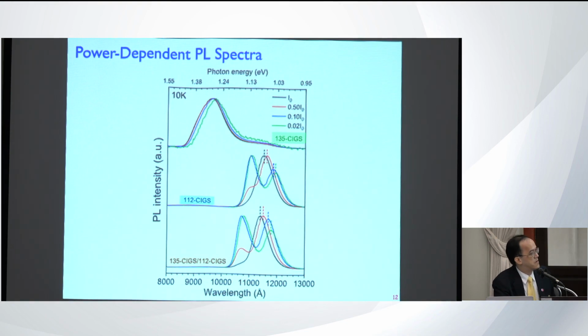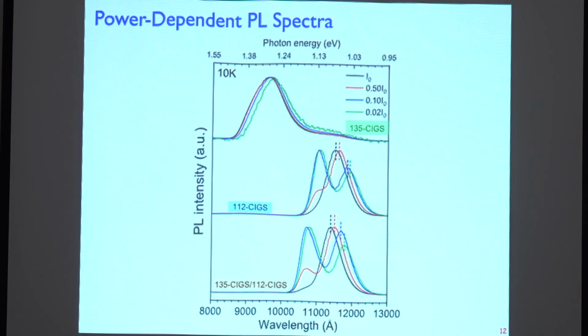First, after we perform the PL measurement of 135 with power dependence, meaning we can adjust the power of the laser, the black curve is the highest intensity, down to 20% of the maximum intensity. For the 135, we don't see any difference except a small shift. We saw a broad peak for the luminescence in 135, but in 112, when we reduce the power of the laser, at the highest power we saw one sharp peak, but as the laser power decreased, the peak split, and those are assigned to free to bound and donor to acceptor pair, or DAP.